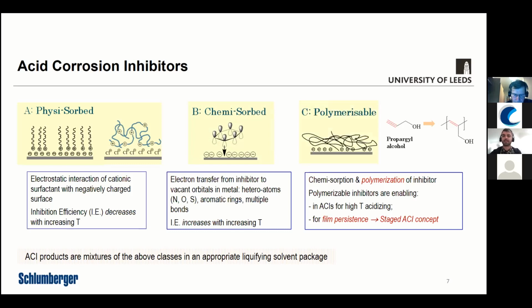And then finally, polymerizable inhibitors. So this is when the inhibitor adsorbs to the surface, it forms a film, and it polymerizes in the environment that it's in, essentially establishing that film, strengthening that film, and it becomes a more protective corrosion inhibitor. And propargyl alcohol is an example of one of those inhibitors. Polymerizable inhibitors, therefore, because of the acidic environment, and acidity would promote the polymerization process in this case. The polymerizable inhibitors are favored for protection of carbon steel in matrix acidizing operations.